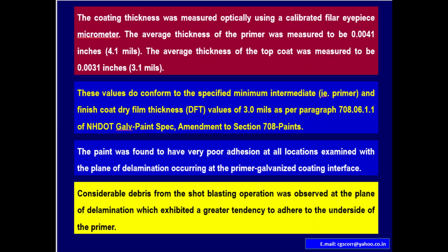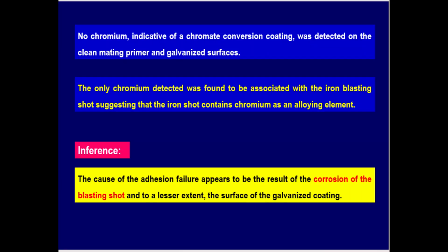The paint was found to have very poor adhesion at all locations examined, with the plane of delamination occurring at the primer galvanized coating interface. Considerable debris from the shot blasting operation was observed at the plane of delamination, which exhibited a greater tendency to adhere to the underside of the primer. No chromium indicative of a chromate conversion coating was detected on the clean mating primer and galvanized surfaces. The only chromium detected was found to be associated with the iron blasting shot, suggesting that the iron shot contains chromium as an alloying element.